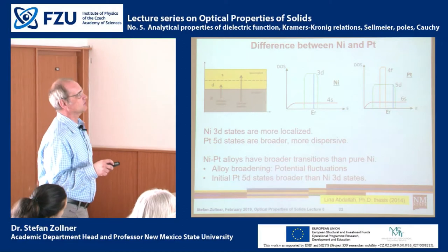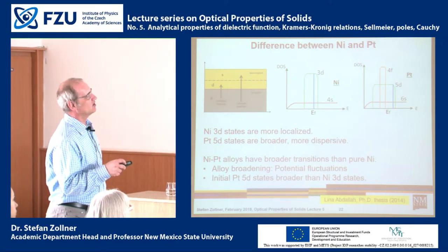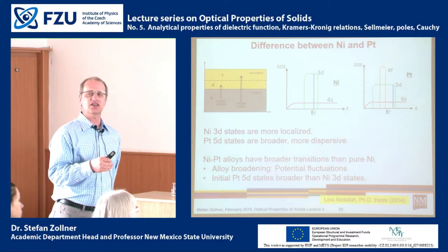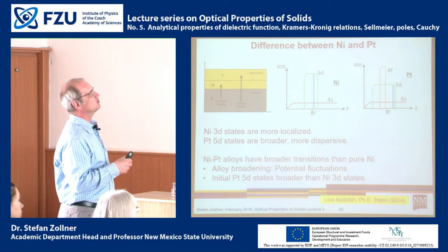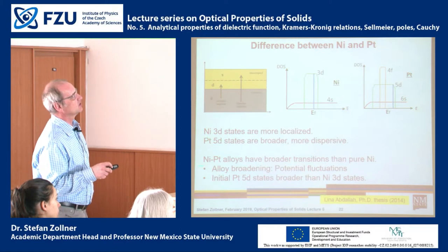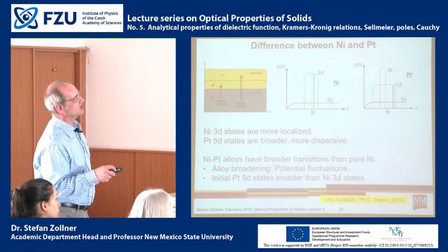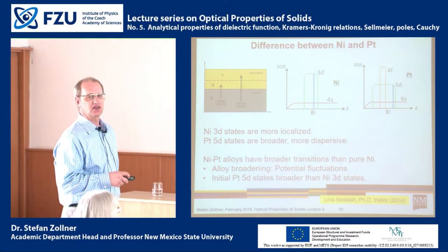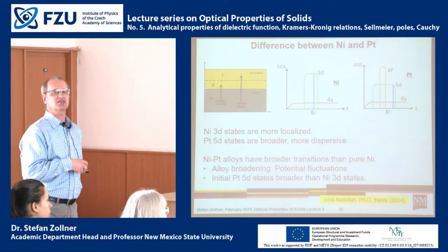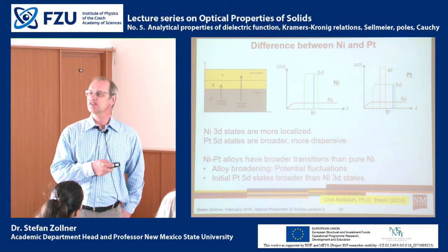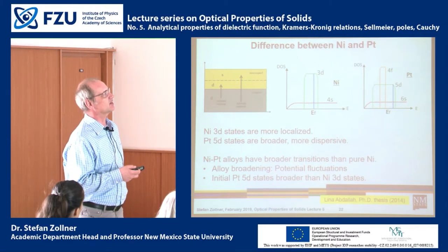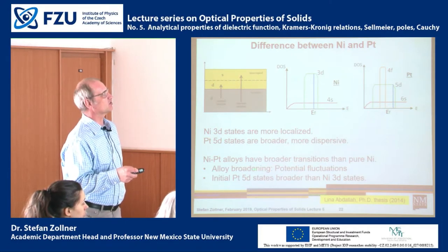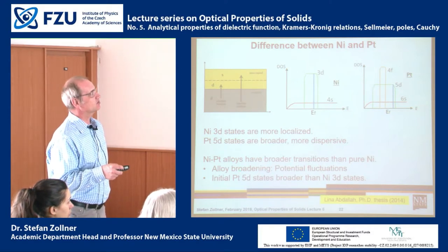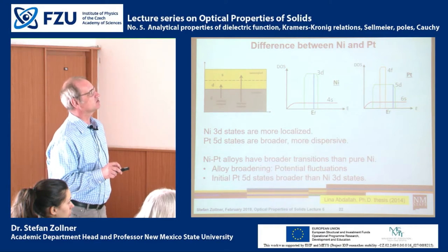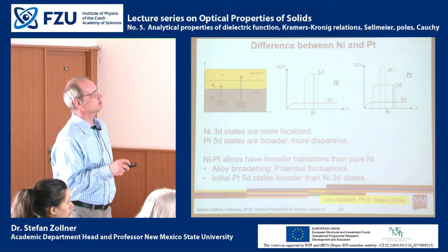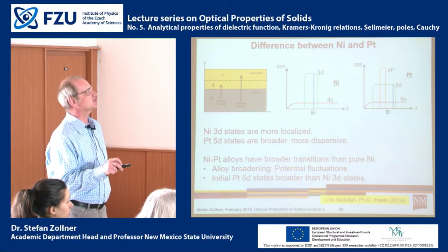And we can look at that when we study nickel-platinum alloys. In an alloy, there are two effects. There is the chemical variation as you go from one material to the other, so you can do some sort of an interpolation between nickel and platinum to understand the alloy. But the other effect is that because you have an alloy, you have potential fluctuations. The nickel potential is different from the platinum potential, so your crystal is no longer periodic. This deviation from periodicity gives you a scattering, which we call alloy broadening. So both of these effects come into play: the alloy broadening, and the difference in the width of the platinum 5d and nickel 3d states.